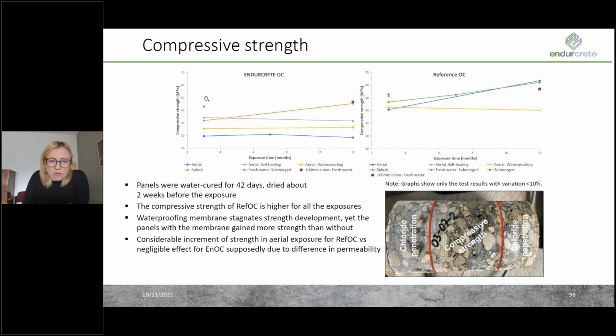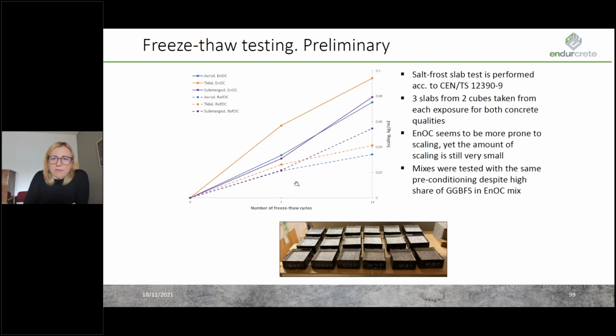Nevertheless, the EnDurCrete offshore concrete performed quite well regarding the frost and the permeability measurements. As well, the coatings performed really well. The frost freezing-thawing testing results are presented in this graph. As you can see, again, the reference offshore concrete performed a little bit better, but overall, all concrete samples performed very well regarding the frost degradation problem.